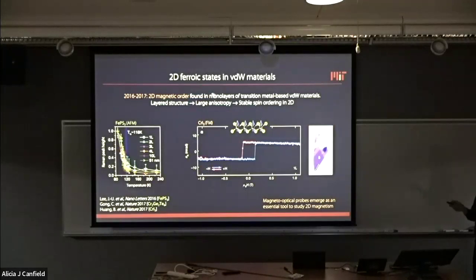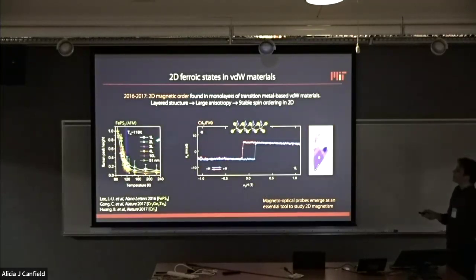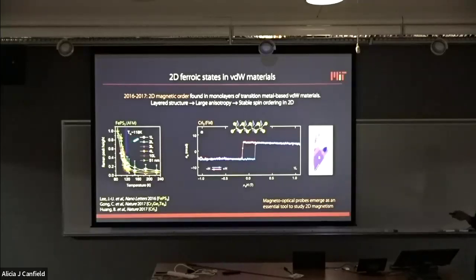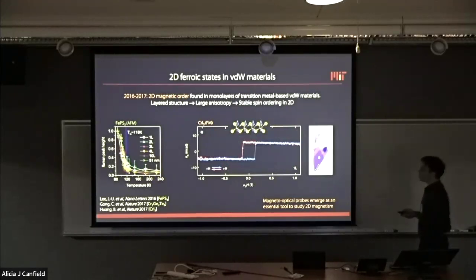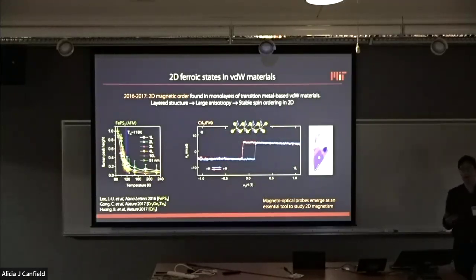Just a year later, 2D magnetic order was discovered. This was originally found in a 2D antiferromagnet, so in the single unit cell limit of this iron phosphorus sulfide antiferromagnet. This was a Raman measurement. But then the big breakthrough came with the discovery of 2D ferromagnetism in chromium iodide and a few other materials in the single layer limit, using magneto-optical probes as a way to look at magnetism. Looking at magnetism, same as ferroelectricity in the ultra-thin limit, is very challenging because of the very, very small sample volume and number of spins. So traditional techniques such as magnetometry or even SQUID magnetometry have a really hard time. But magneto-optical probes really emerge as an essential tool to study 2D magnets.